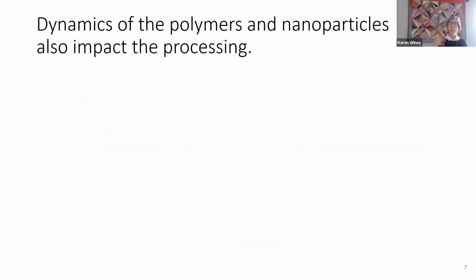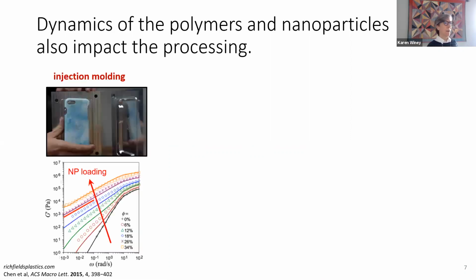It's also very important for processing. So how far particles move during the processing will indicate whether or not they actually bump into one another. And once they bump into each other, they're likely to agglomerate. So for injection molding, as you increase the particle concentration here, you're getting a much more viscous system, and that will impact its ability to fill fine parts. This is very important for the automobile industry.